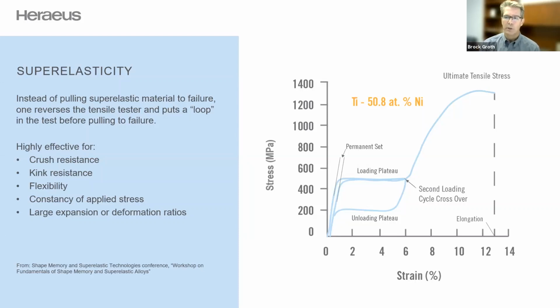And so the strains are reversed and the force, or the stress, drops dramatically right off the bat. And then it gets to this unloading plateau, and it's basically the opposite of the loading plateau. Now the material is contracting, but the force is very constant. And then it gets down again to 1%, metaphorically in this example, and the force drops back down to zero. There is a tiny bit of permanent set here.